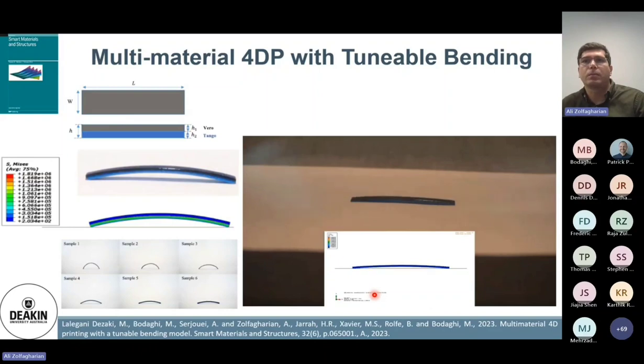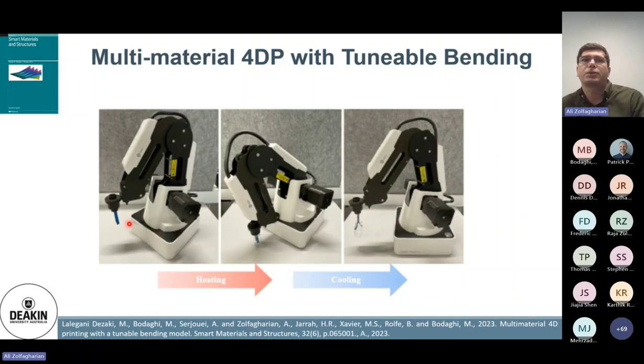And we also developed the simulation part specific to the 4D printing of these two layers, in order to reversely be able to predict the bending behavior of this composite 4D printing material that we achieved. And we successfully showed the application. For example, again, with fragile objects, like the glassware you could see in the lab, when we applied this gripper and heated it up, it started bending and could carry this payload. Even using conventional robotics, we bring in these soft grippers or soft actuators, using 4D printing as an application.